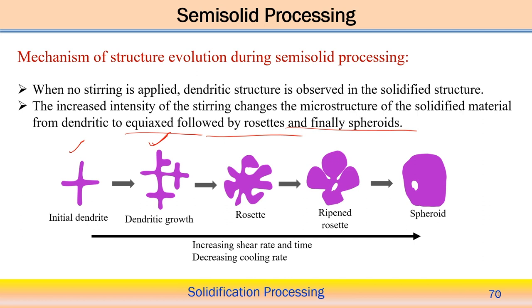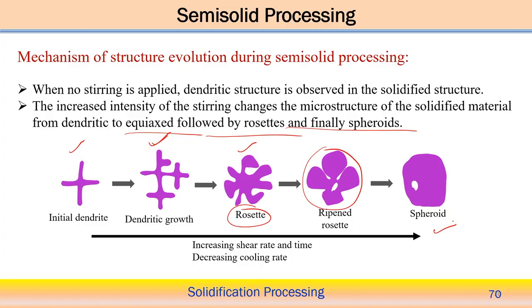Now, with the application of mechanical shearing, it creates a rosette kind of structure. You can see this kind of structure usually forms. Further, the ripened rosettes look like this. Then it is converted to a kind of spheroid, and finally it tends to form a more or less equiaxed grain structure after the complete semi-solid processing of a particular material. Here you observe the increasing shear rate,